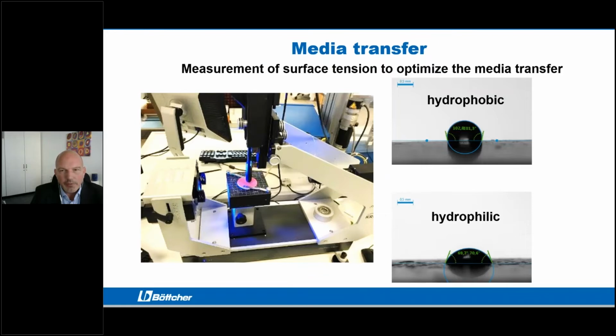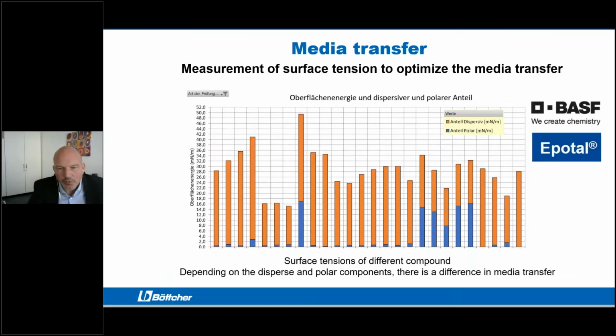We can do also measurements of the surface tension of our materials. So there we have, for example, hydrophobic or hydrophilic behavior of the rubber and of the media which we put in contact. This is also important to optimize, for example, the transfer of the media in the application. Here's just a short picture, so we can measure different surface tensions and find, for example, for the products from BASF, the optimized compound to make it possible to use it in the process. For example, in this case of the dispenser position in a lamination station.